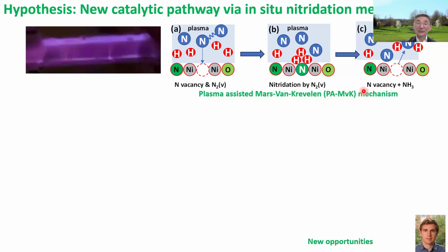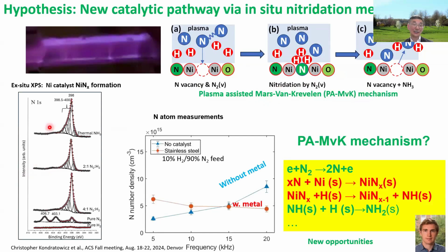And what is the evidence? In experiment, we put nickel into a hydrogen plasma, and you don't see any nitride on the nickel. When you put in nitrogen, you start to see some nickel nitride formed, but also a lot of oxides. But if you add a little bit of hydrogen, more nitride is formed, close to ammonia. This is very encouraging that the plasma-assisted MvK mechanism may be happening. And hydrogen can increase the nitridation.